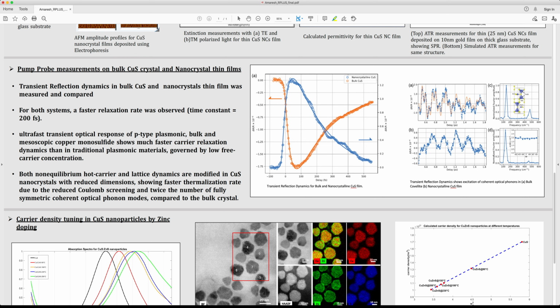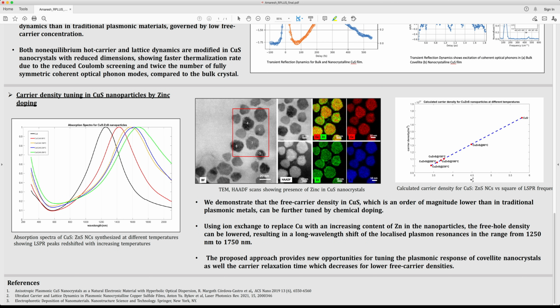Finally, we also demonstrate experimentally that the LSPR in copper sulfide nanocrystals can be tuned in a wide range and with a good reproducibility by doping these particles with zinc using an ion exchange synthesis procedure. The resulting particles show a consistent redshift in their LSPR peaks as the ion exchange synthesis temperature was increased, which we attribute to increased zinc doping.